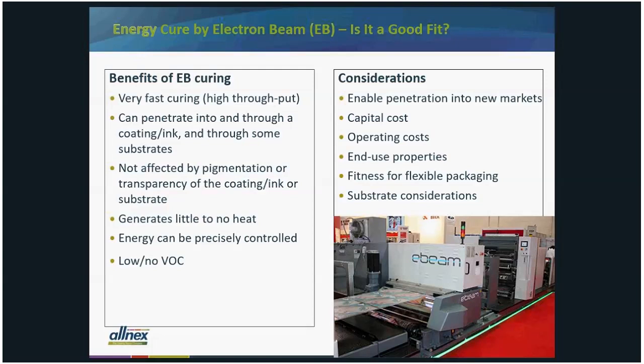As far as end-use properties goes, here's where it gets a little bit more granular. The end-use property is going to be really specific to the formulation and your end use. But some of the things that you can expect using electron beam are better surface cure, so a harder, more scratch and abrasion resistant surface. And if that's something that can allow you to expand your market, that's a benefit. There's fitness for flexible packaging because we mentioned before, electron beam does not use any photoinitiators. Coatings will have fewer extractables, which is a big plus if you're going to be in the flexible packaging market. And again, because of the low heat, you might be able to use substrates which before were out of reach because of heat sensitivity.